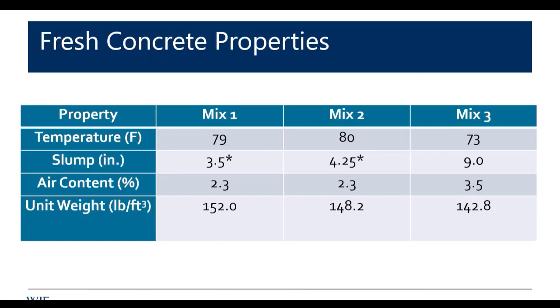Fresh concrete properties, this is as they were delivered and tested on site. One thing to notice is mix 3 started off cooler. It had a very low water cement ratio, less water, heat was being put in by boiling or heating the water. So we started later in the day with a lower temperature on mix 3. Slumps, these were measured later, so they had lost some slump. That's what the asterisk said, that would have been here. And then basically, this one was coming in, eventually dialed in a pretty high slump. Air content's a little bit high on mix 3 than we wanted, and that reflects in the lower unit weight.